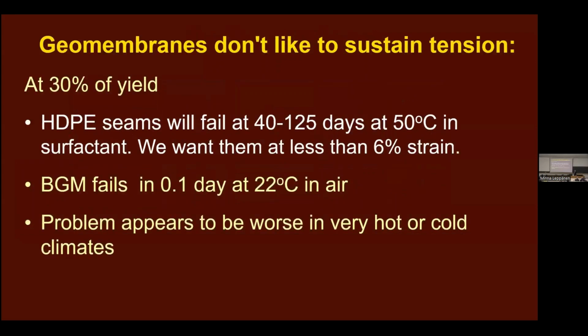HDPE seams will fail in 40 to 125 days at 50 degrees C in a surfactant. And we want them at less than 6% strain. BGMs fail in 0.1 of a day at 22 degrees in air. And the problem gets worse in very hot and very cold conditions.